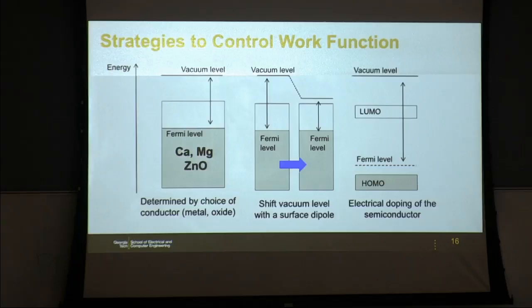The other way, and I've discussed that many times in the past, I won't today, is that you can pull down the vacuum level by creating a surface dipole, so through surface modification. Or the other way where you can change the work function is to take one of these semiconductors and electrically dope it. If you have P-type doping, and you add holes into that HOMO band down here, so you bring the Fermi level energy closer to that HOMO band, you'll end up with a material which has a high work function. On the other hand, if you n-dope it and you bring it up here, you get a material that has a low work function. And in addition, because these materials are electrically doped, they're also electrically conductive, and so they serve both purposes. You control the work function, and you also have a conducting material.